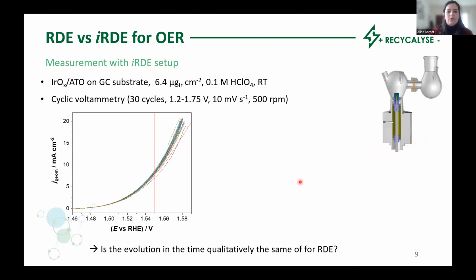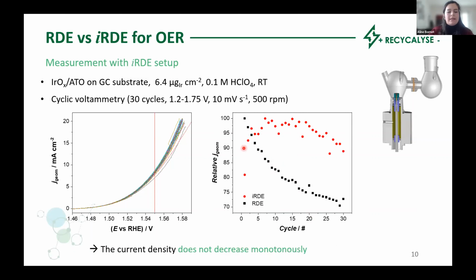Then we did the same experiment with the inverted setup with a fresh electrode. And the question now is, how is the evolution at this potential of 1.55 volt? And we see that the evolution is not the same, and we don't see this rapid decrease as we saw for the traditional configuration. We observe instead a rather plateau-like behavior with some jumps and oscillations that correspond to bubble detachment.